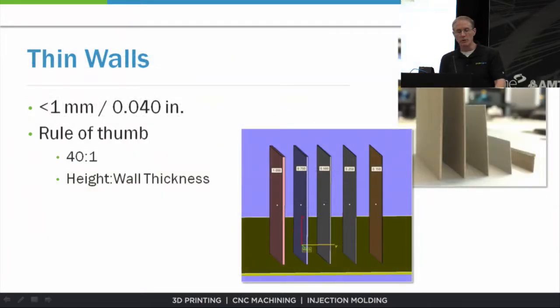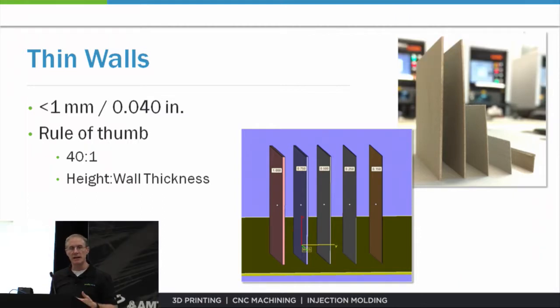So we're looking at it in the context of thin walls. What we've done here is we've put a CAD file together that has a 2-inch tall wall, and we printed it at varying thicknesses, right? The one on the far right, as it's CADed up, should be 0.1 mm. And they progressively get larger up to 1 mm on the far left, or 40/1000ths of an inch. What we really wanted to test here is, what is the ratio of thickness to height that you can reasonably achieve with your part designs and expect success in the DMLS process.